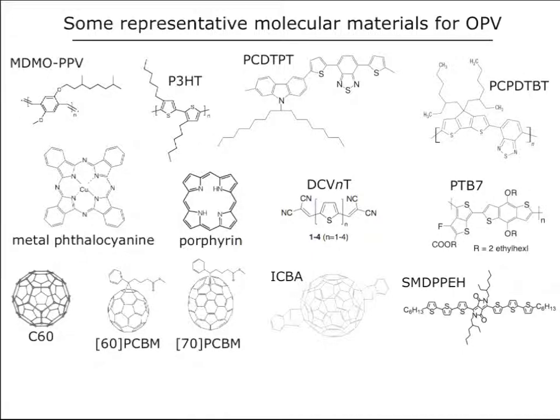So more recently, more sophisticated materials have been developed. And these are typically copolymers that take advantage of an intramolecular charge transfer to reduce the band gap, something closer to 1.4 electron volts. So a couple commonly used materials, PCDTBT, PCDTPT. I just reversed those, but you get the idea. PTB7, these are all various copolymers. And frequently you will see this benzothiadiazole moiety, benzene with this diazole. So that is a good electron acceptor that acts to reduce the band gap within the material.